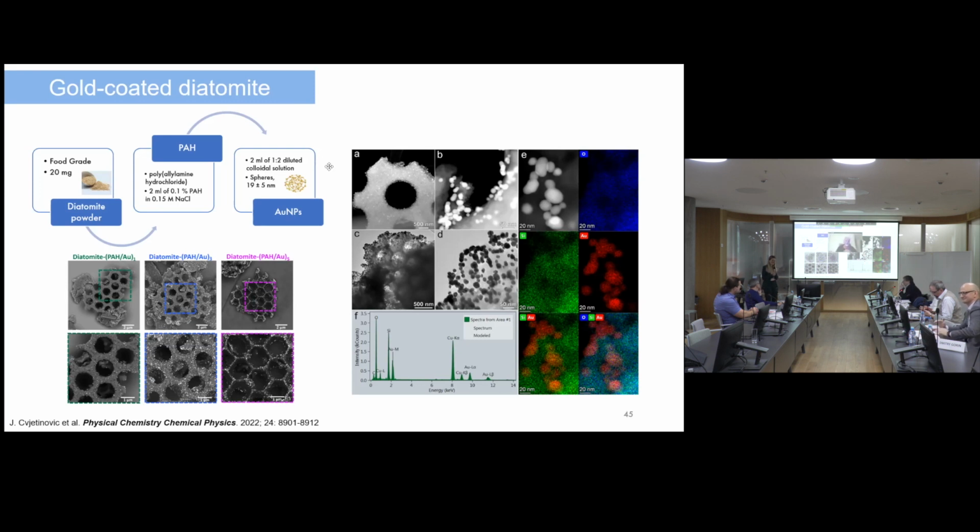Yes, please. Go ahead. Okay, I saw a lot of comments about optical property. I worked on this problem a very long time ago. So it's very important to consider here the plasmonic and waveguiding properties of the structure of diatoms. When I did an experiment hitting only diatoms with a very small laser spot, 1 micron, on the edge of the diatom structure, all the chloroplasts started to light up.